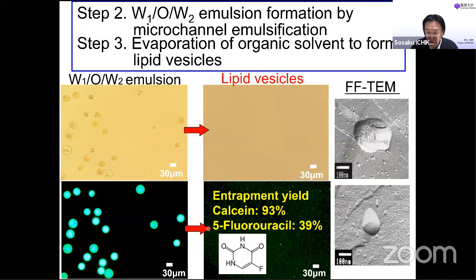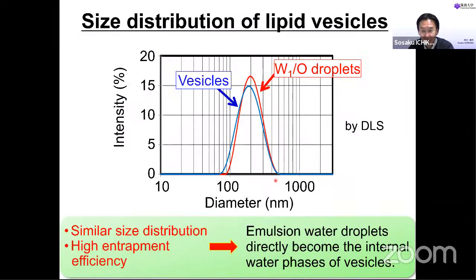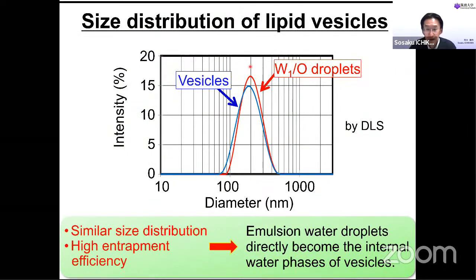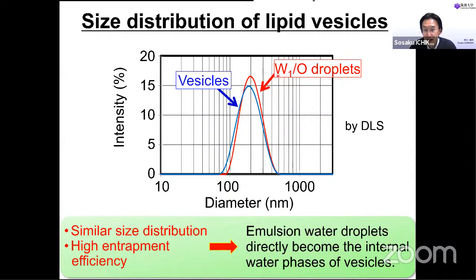For 5-fluorouracil as a cancer drug, it is around 40%. This entrapment is relatively high compared to the other preparation methods. This is the size distribution. It's the same. The size of the prepared lipid vesicle is the same as the initial size of the water droplet like this. So we can control the size and we can achieve high entrapment efficiency by using this method.